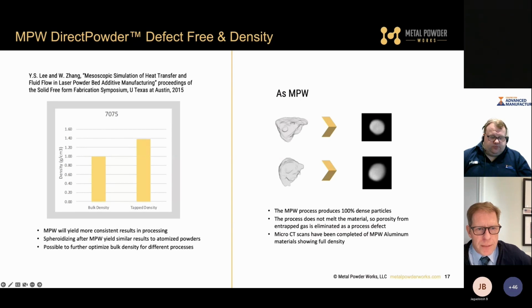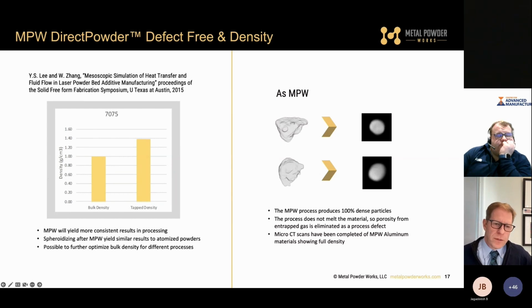and tap density is interesting. So these are some of the measured values that we have. It goes back to the previous discussion about the rotating drum. The rotating drum is more suitable for a powder bed or binder jetting environment than the Hall flow is, because rarely do you have an instance where you're flowing powders through a circular orifice, specifically a very small circular orifice. So it's a proxy for what we want, which is powder movement. We've done some CT work with the University of Pittsburgh. We've taken our powders and we've also spheroidized them.